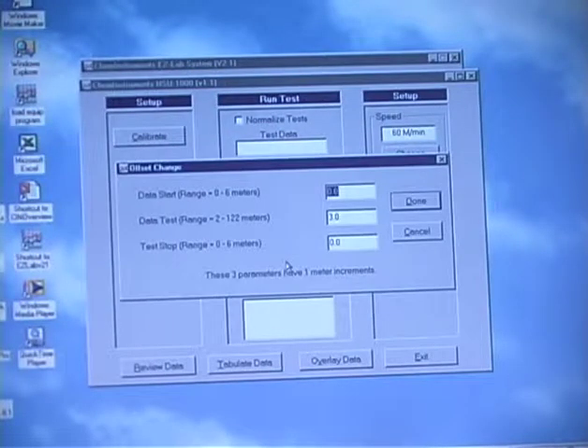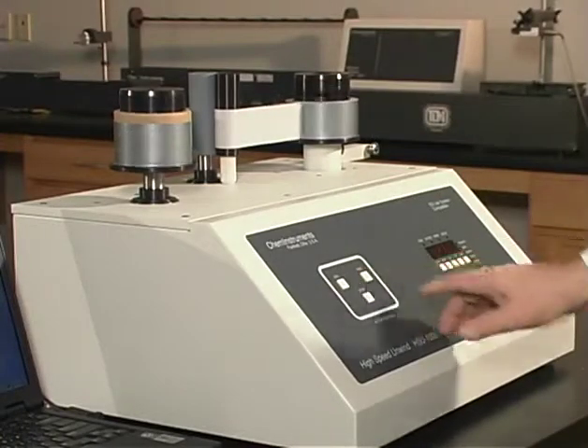Set the high speed unwind machine for a 60 meters per minute unwind rate and start the test.